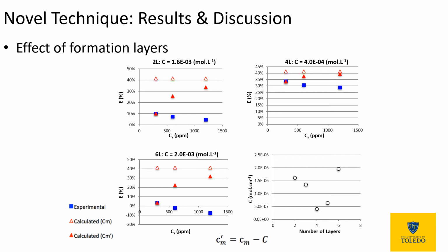So we estimated that portion of the salt in the membrane that is unable to move freely, that is tied up with the membrane structure itself, by looking at the very first enrichment point that we measured experimentally, and comparing it to what we predicted theoretically with no immobilization. We determined the amount of immobilization that would be needed to bring that first point in agreement with the experimental data.